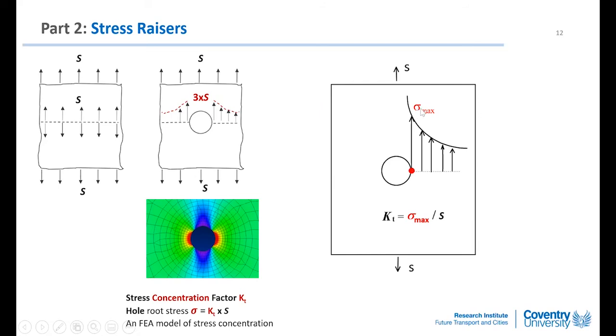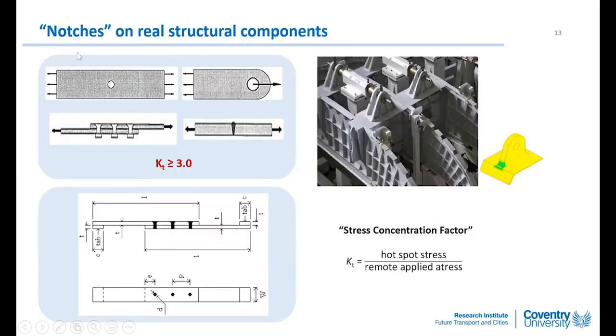The hotspot stress, sigma max, divided by the applied stress is the stress concentration factor. In my field, we call this the notch effect. It doesn't matter whether it's an open hole, a pin-loaded hole, a riveted hole, or even a welded joint. We just call it the notch effect. If you look at the dictionary, a notch is an indentation, a dent. The notch does have an effect on structures because it has a stress concentration.